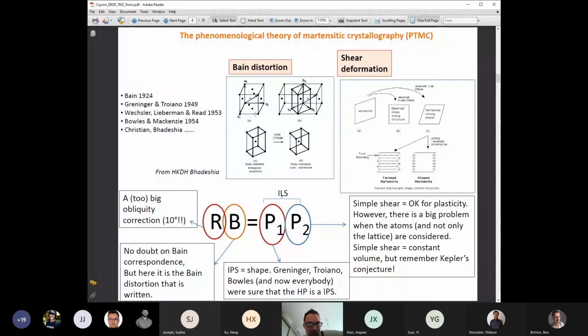Okay, but if you look at the Bain schematic representation, just at the Bain distortion, you can use a matrix B to represent this distortion. Well, it's not what you observe experimentally. We observe an orientation relationship that is not B, but is B composed with a rotation of around 10 degrees.